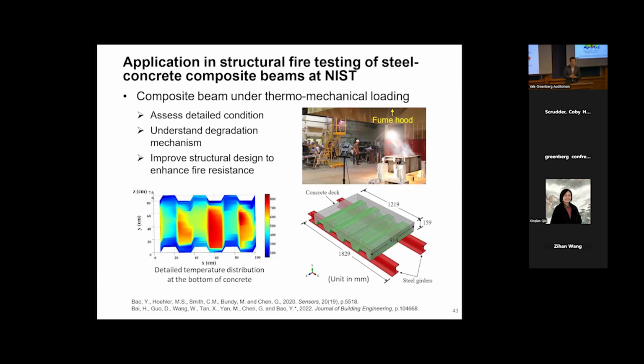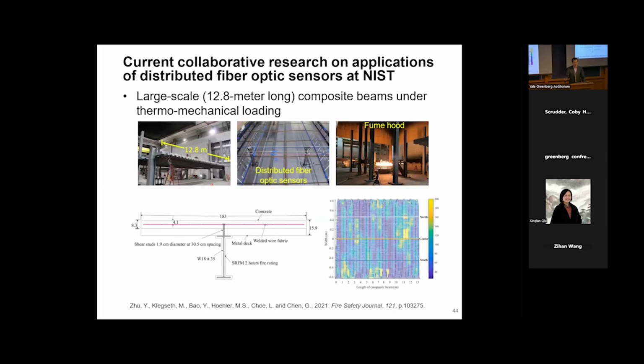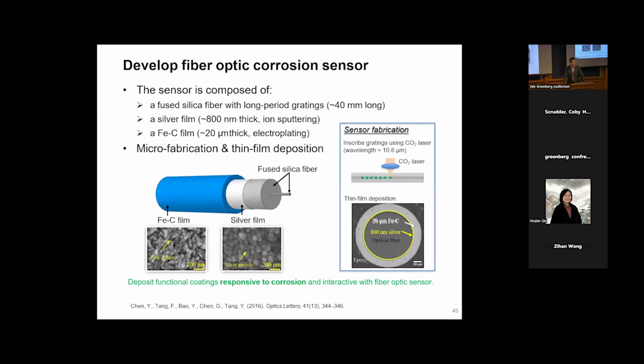Because in fire, there is a very complex temperature distribution. As Professor Nino said, fire dynamics is very complex. So it's very difficult to predict the temperature distribution within a structure, like in a building. But if we get accurate measurements of temperature, and we know the relation between temperature and the mechanical properties, we can very accurately predict the structural behavior, like what will be the failure time and what will be the remaining life. Based on the success of the small-scale testing, we did some large-scale testing in the National Fire Research Lab at NIST. We got good results.